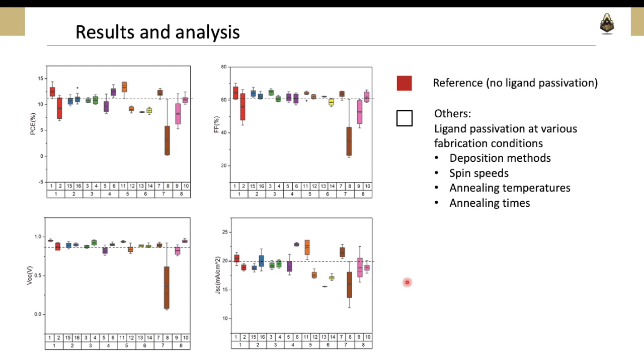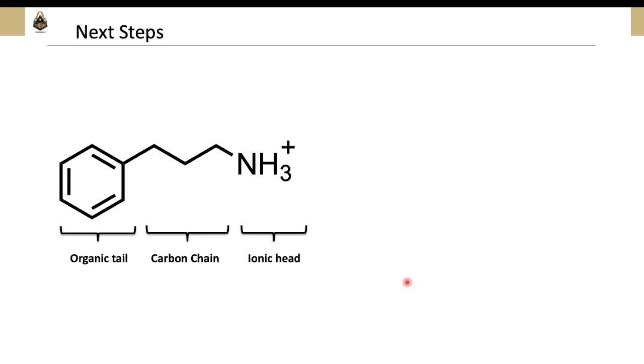In the next step of my research, my goal is to analyze and test different ligands, tune the thickness of the 2D perovskite layer by varying ligand solution concentration and thin film annealing conditions. We can detect the 2D crystal structure using techniques including X-ray diffraction and its emission using photoluminescence spectroscopy. Furthermore, we can characterize the ligand penetration depth using angle-dependent X-ray photoelectron spectroscopy and time-of-flight secondary ion mass spectroscopy. By characterizing and monitoring the perovskite film over time, we can understand how the ligands influence device performance and stability.